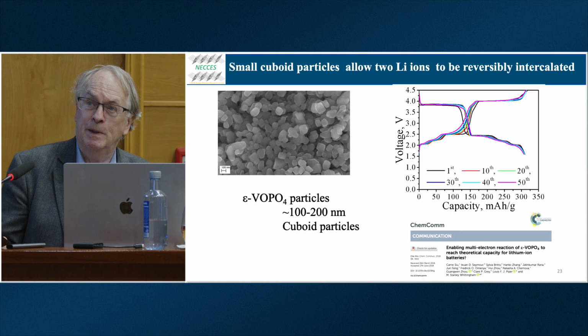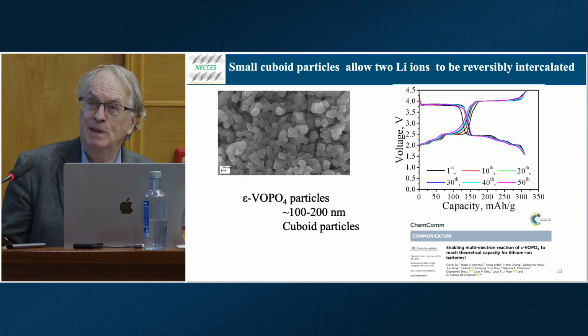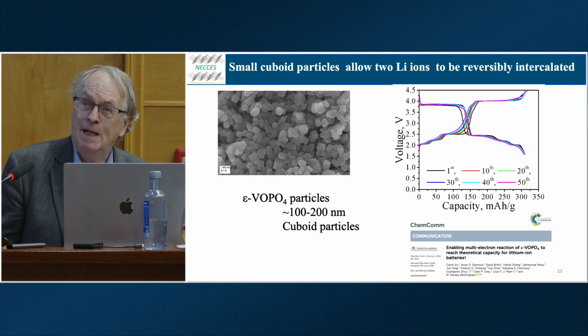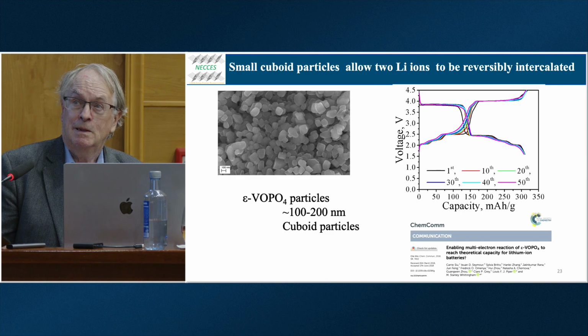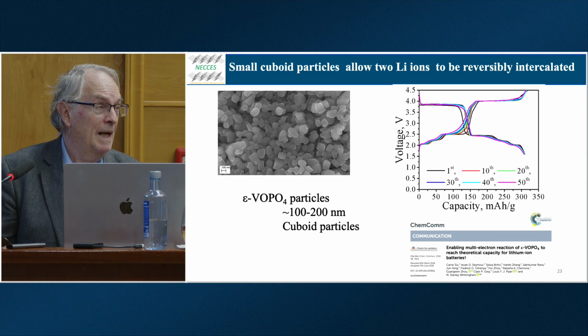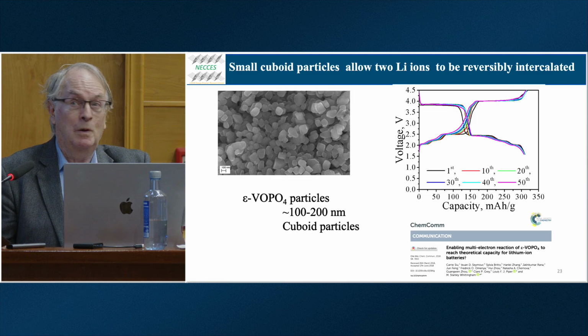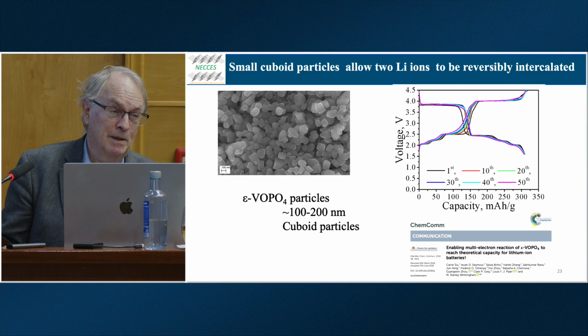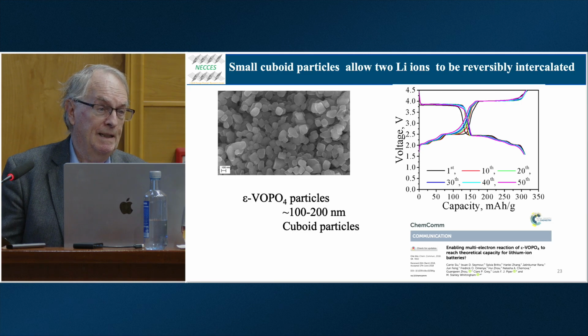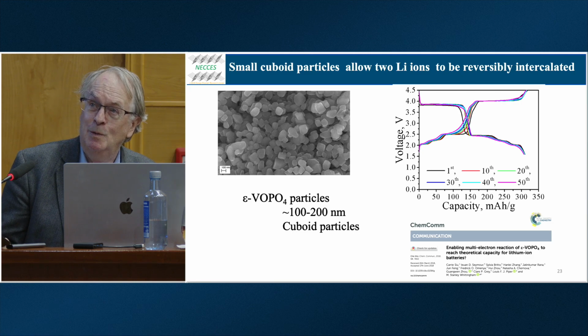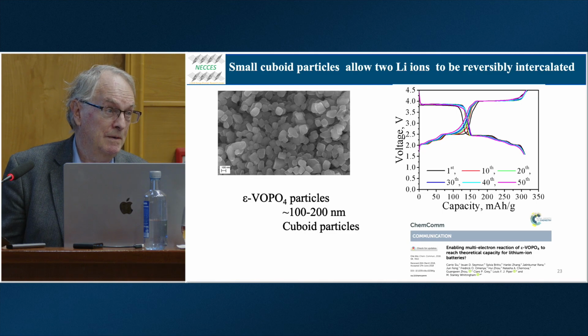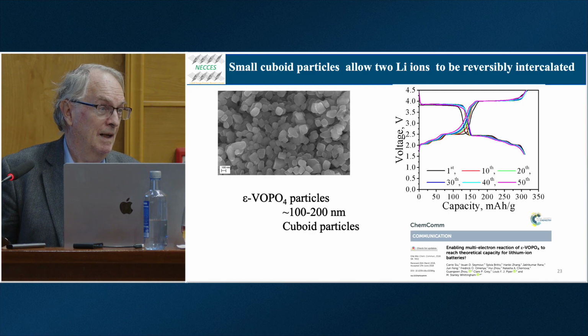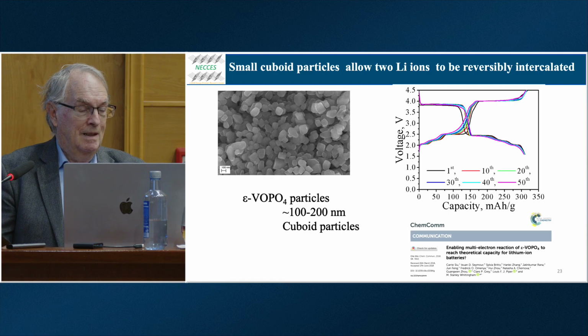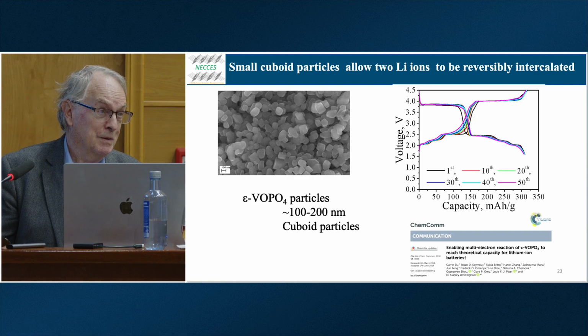So what we end up with are these little cuboids. They're about 100 to 200 nanometers in size. And when we cycle those, we get the typical curves shown here. You can see the 4-volt plateau is vanadium 5 to vanadium 4, and the 2.5-volt plateau is the vanadium 4 to vanadium 3. And if you look closely, the black curve is the first cycle, first time we put lithium in and out, and the purple one's the 50th cycle. And you can see the 50th cycle is in fact better than the first one.